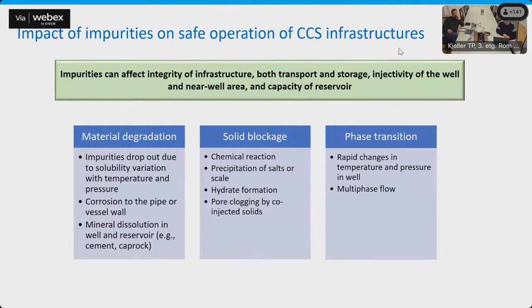Another hazard is solid blockage. The solid particles can come from chemical reaction, precipitation of salts and scale. When the temperature and pressure are in the hydrate formation zone, hydrate particles may also form. Some solid particles just come from the capture site. So those solids can clog and reduce the injectivity of the well and near-well region, and then reduce the capacity of the reservoir. If those solid particles block the venting valve, people can have a risk of unsafe operation of the pipeline, for example.